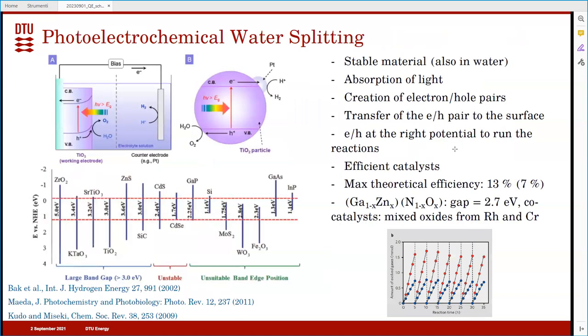So the first example was this gallium nitride zinc oxide in late 2010 or so, where you have a material that is able to absorb light and create an electron-hole pair. The electron-hole pair reaches the surface. The electron is used to evolve hydrogen. The hole is used to evolve oxygen. So it's kind of a tricky problem because you need a material that is stable in water, with good light harvesting and good catalytic properties. So this is not so trivial.